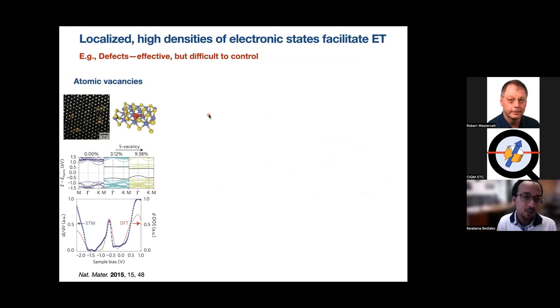There are other ways that our community has developed to control and facilitate charge transfer. One is by using defects. So it turns out that defects, which you often maybe think of as the undesirable properties of surfaces, can be really effective at mediating interfacial charge transfer, because they create localized electronic states that are available to participate in that reaction at a suitable energy.